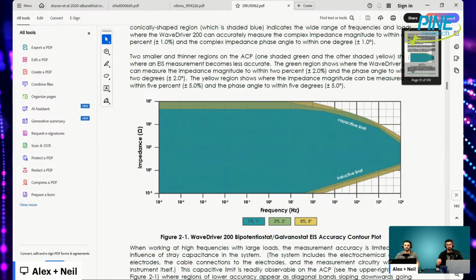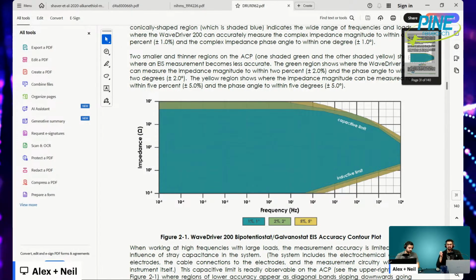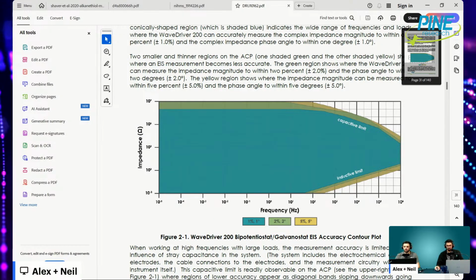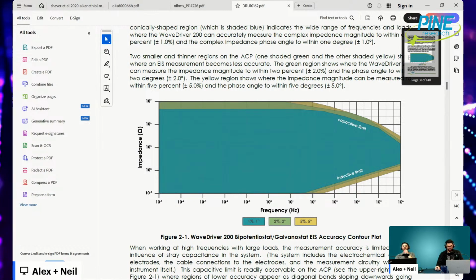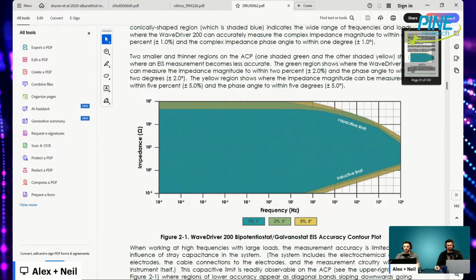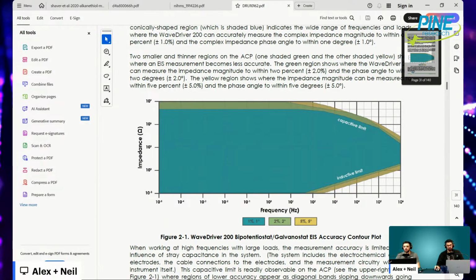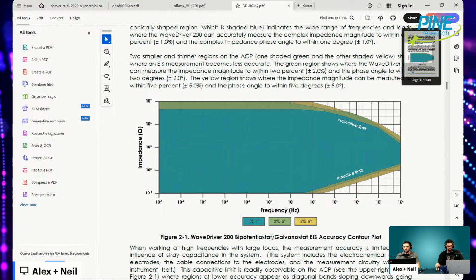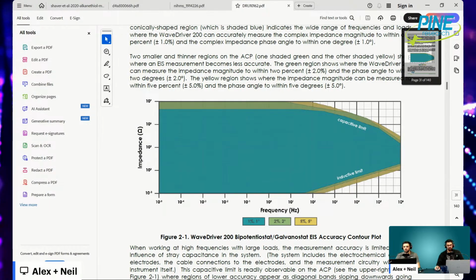It goes from 1% and 1 degree, because there's also the phase. The phase angle is another thing of accuracy that you need to be aware of when making your EIS measurements. And then after a certain point, you have 5% and 5 degree accuracy. But then at a certain point, if you're measuring things with very low impedances or very high impedances, your accuracy will decrease. So when it comes to the accuracy of the measurement, besides just the time resolution and sampling, there's another limitation in terms of accuracy, which is based on this accuracy contour plot. So that's just another thing to keep in mind as you're doing your experiment, basically.